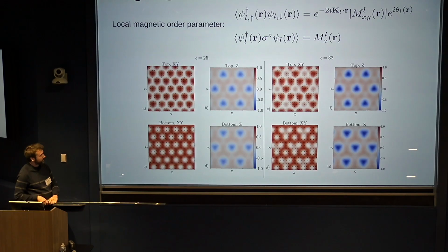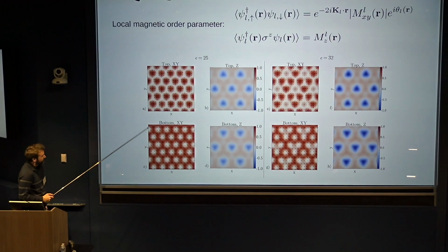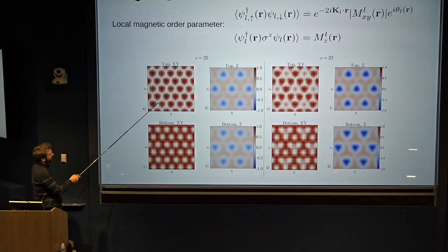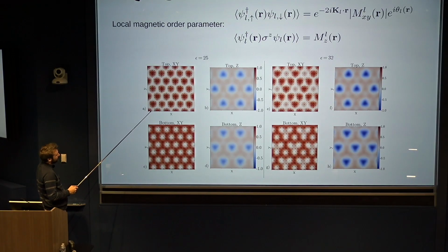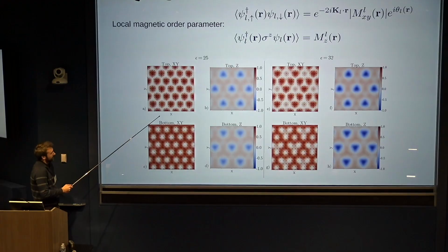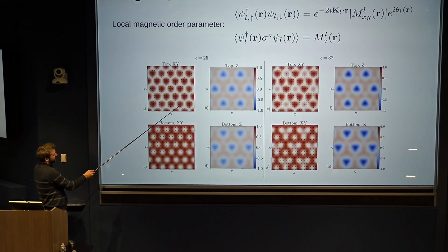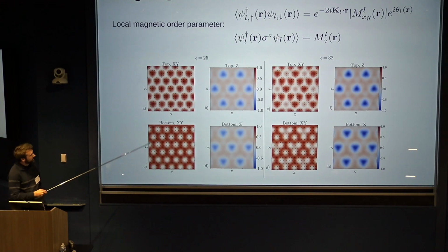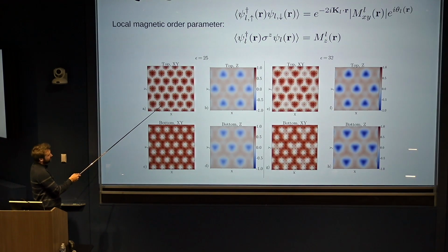Okay, good. So first, what does it look like? Here on the top left plot, I'm showing the in-plane magnetic moment as a function of the spatial coordinate, so this is a real space plot. These red blobs represent the size of the in-plane moment, and the black arrows represent the direction of the in-plane moments. This is on the top tungsten diselenide layer, and this is the bottom tungsten diselenide layer.